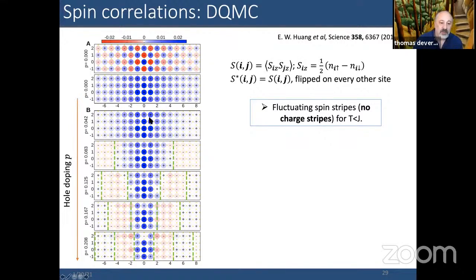But then when one dopes, the correlation length changes a little bit, but you still get persistence of local antiferromagnetic order, but there is a domain wall in which the antiferromagnetic order flips its phase. These green lines denote that domain boundary, and you see that the width between the two domains is shrinking as one dopes, even up to 20, 21% or so. So that's evidence for fluctuating spin stripes. But if we look at the charge in the same light, we do not see any evidence at these temperatures for fluctuating charge order. This occurs as long as one gets to temperatures below approximately J. And we've pushed to lower temperatures, but still no sign of charge order.